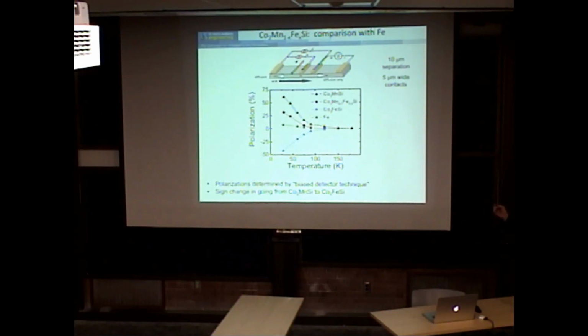So how do you explain the spin injection? The tunnel barrier of the Schottky gives us a spin-dependent resistance. So don't forget, it's not an ohmic contact. It's a tunneling contact, so it's ballistic transport into the gallium arsenide. So that model that said it was all conductivity mismatch is not relevant if I can do ballistic transport going in.